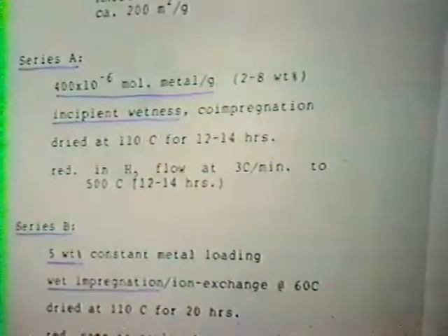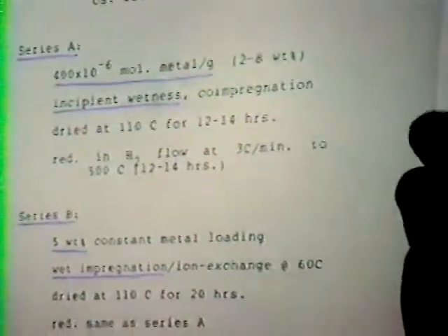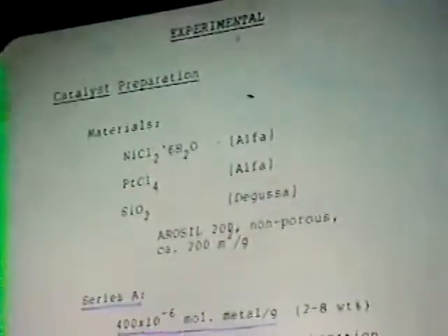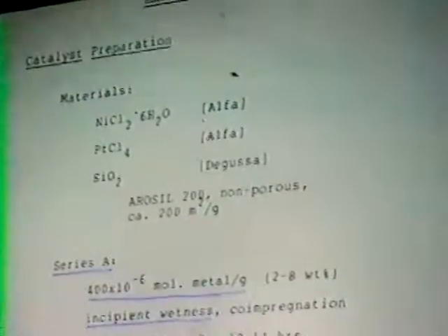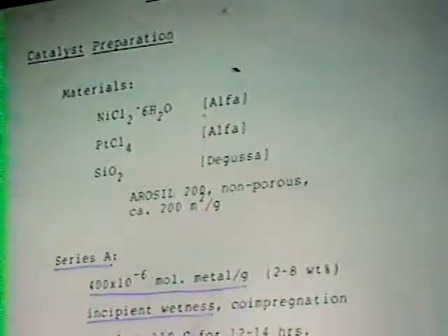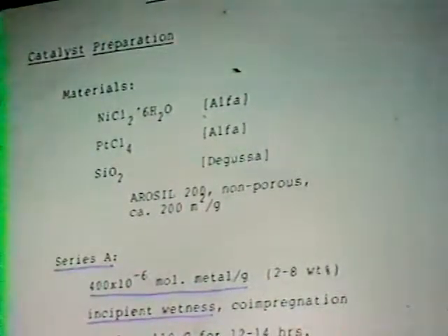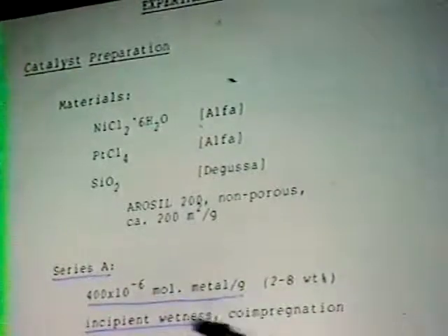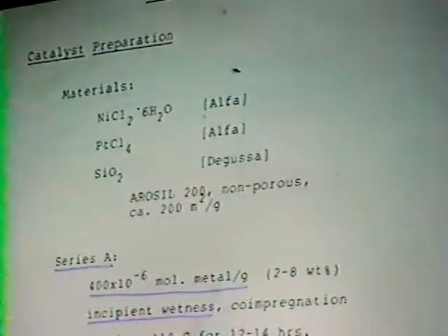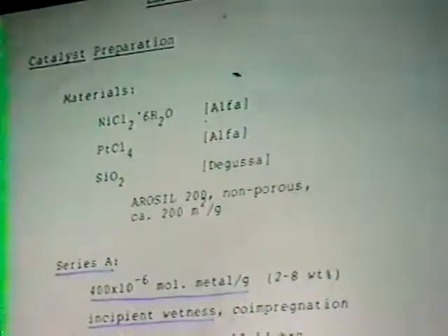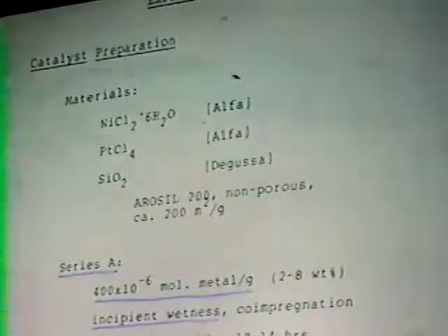In our investigation of this promotion of the reduction of the nickel, we used nickel chloride, platinum chloride, and the Degussa silica, and we had two series that I will briefly mention. One is Series A, which has a constant number of metal atoms on the surface, in terms of 400 micromoles of metal per gram of catalyst, prepared by incipient wetness using co-impregnation.